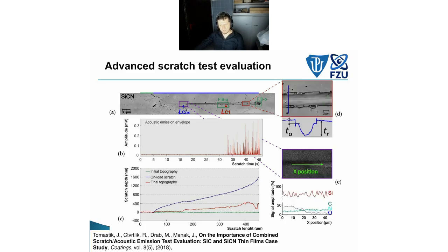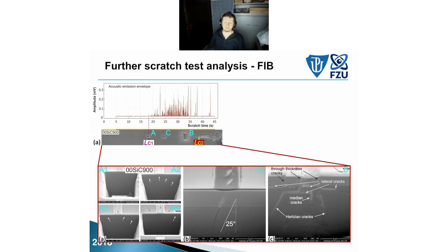We evaluated and confirmed the scratching of the oxidation layer using EDS measurement. We measured this area and saw a decrease in the oxygen signal, which means that we scratched off the oxidation layer. But in the latter part, nothing is happening. We couldn't see any cracking. But practically the only sure method to see the exact point of what happened, if something happened below the coating, was the acoustic emission, which shows us that nothing is happening here until this point. And we can see something in depth change, like a slow increase of depth, but we have a hard time finding the exact point. And I will show you what actually happened, because we have some results from focused ion beam.